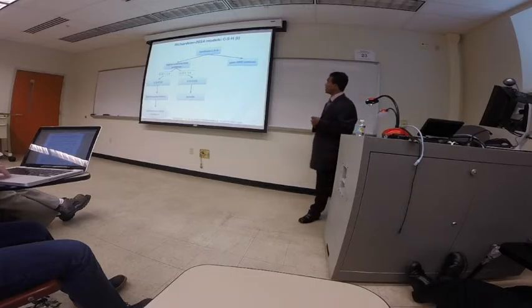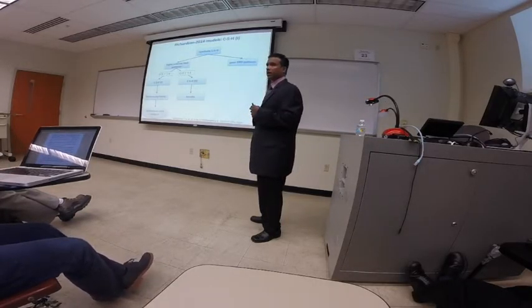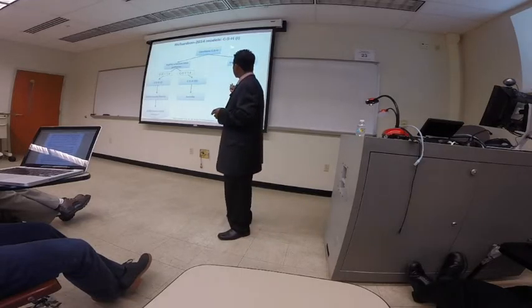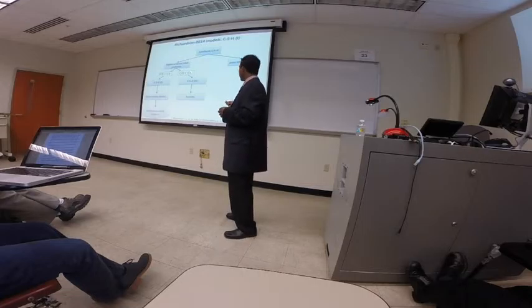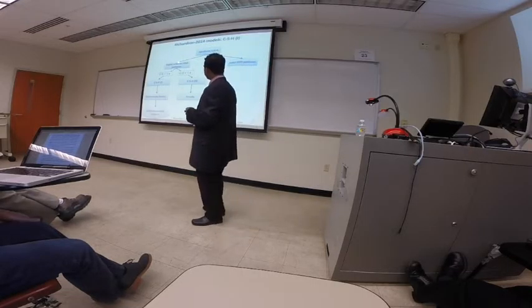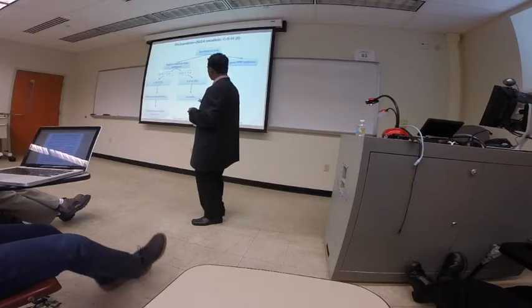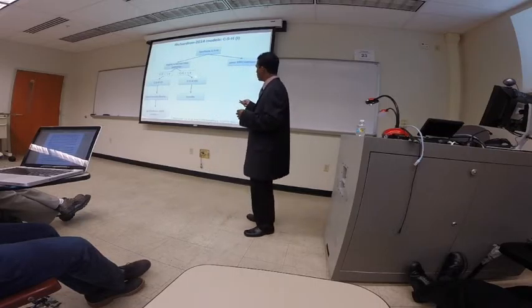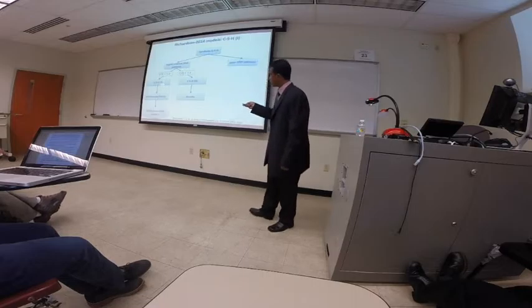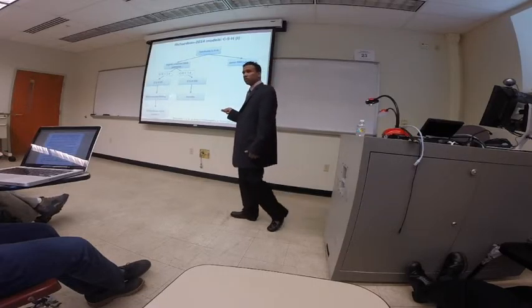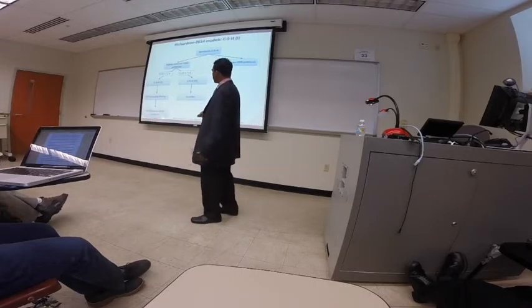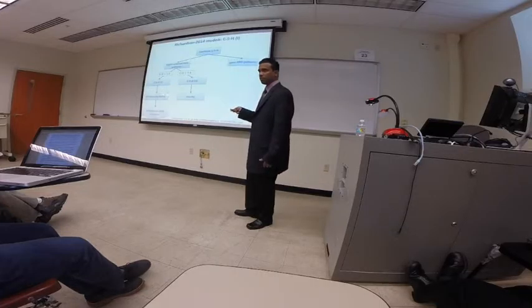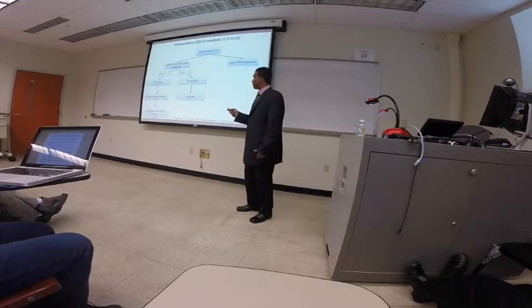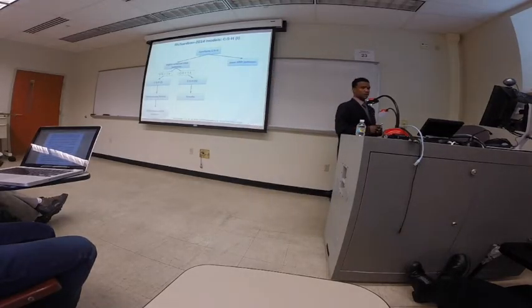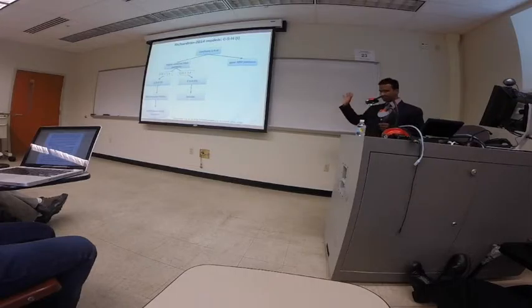So let's go to the Richardson models. As I said, CSH1 type of cement. So let me introduce what CSH1 means. All synthetic CSH can be classified into 2 categories: one that has high XRD patterns, one that has poor XRD patterns. And the higher XRD patterns are grouped into CSH1 and CSH2. CSH1 has a lower C/S ratio and CSH2 has a higher C/S ratio. CSH1 is assumed to be based on the tobermorite family of crystals, the 4 crystals we used in the first study. And Richardson used this family of crystals as a template and made models such that they are consistent with experimental observation. And CSH2 comes from the Jennite family of crystals. Well, Jennite is 1 crystal.